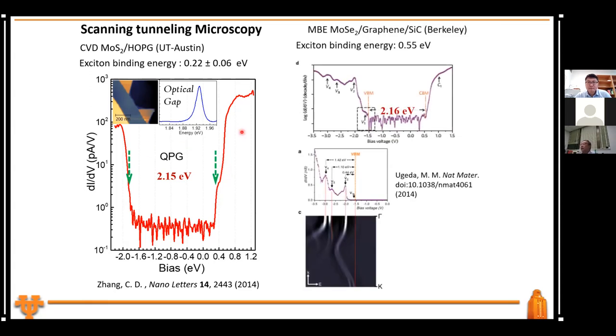And at the same time, the Berkeley group published a paper about 6 months after us. They measured MoSe2. And because it's the same sample that Z.X. Shen used to measure ARPES, they can compare the energy location with the ARPES measurement. They found that this peak is where the gamma point energy peak is. In your typical tunneling spectroscopy, you usually don't see it until, for example, you use a logarithmic scale, then you will see this extra shoulder, and they assigned that to be the valence band.